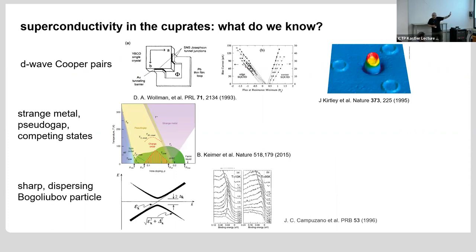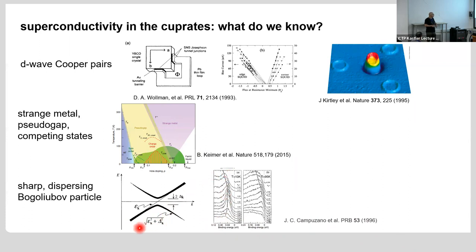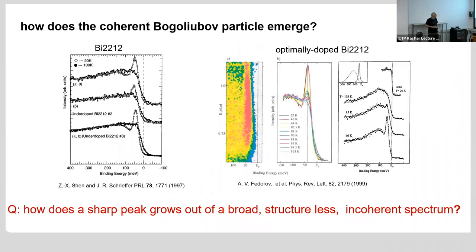There are certain things about complicated superconductors, such as the high-TC superconductor, that we actually understand. We understand that they are, for example, D-wave superconductors. We understand that the phase diagram is a mess, but they form Bogoliubov quasi-particles. This is a photo-emission result taken by the Argonne group, where you see the dispersion and the backwards bending as you would expect for Bogoliubov quasi-particles in a BCS-type theory.